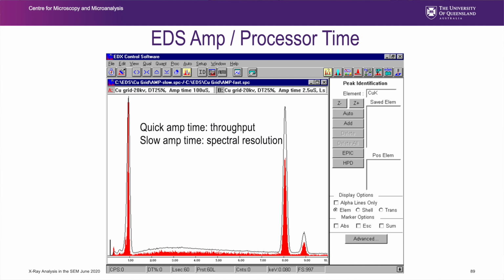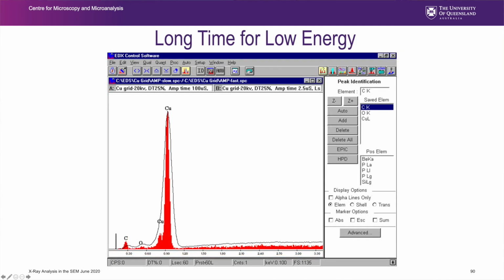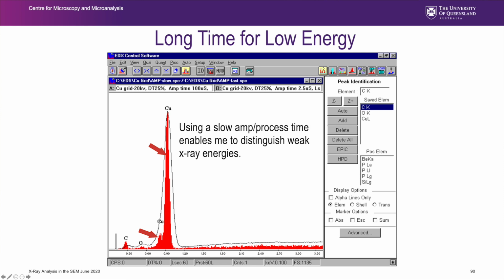You can look at the copper K alpha, and all you really see is a change in height, no significant things. But let's look at the copper L alphas. If I zoom in on the L alpha region, you can actually see there's two little copper peaks there. The L alpha is composed of multiple peaks. When I do slow analysis, long amp time, long processor time, I actually begin to distinguish these weak X-ray energies.